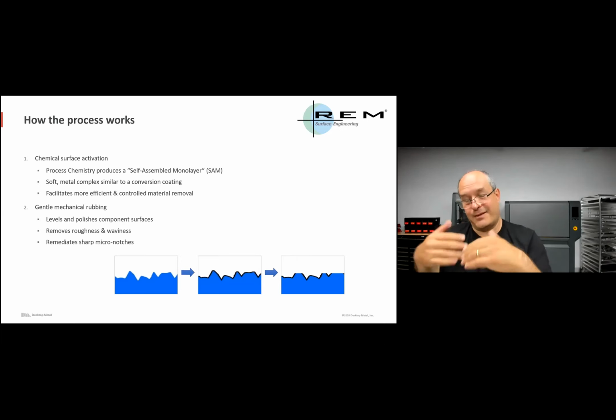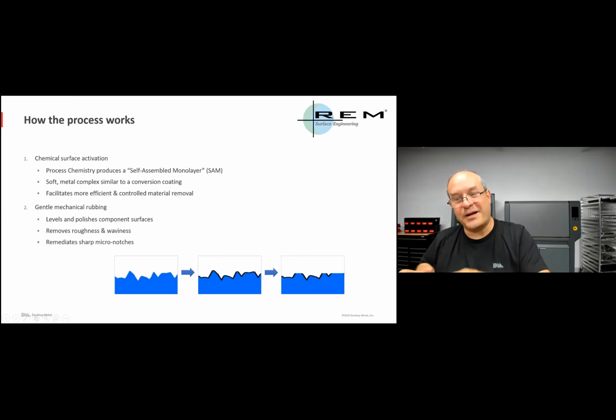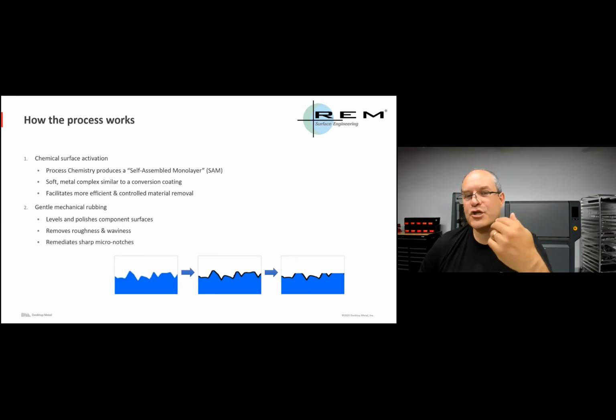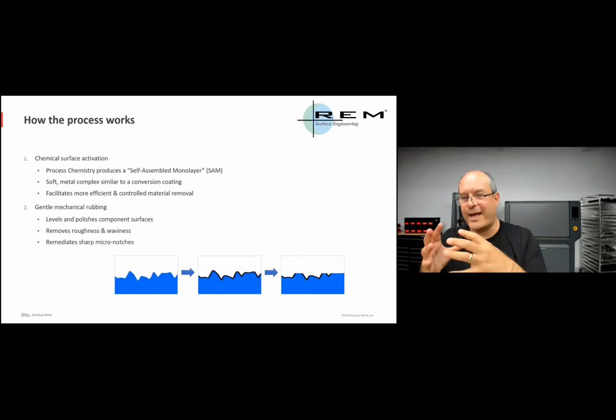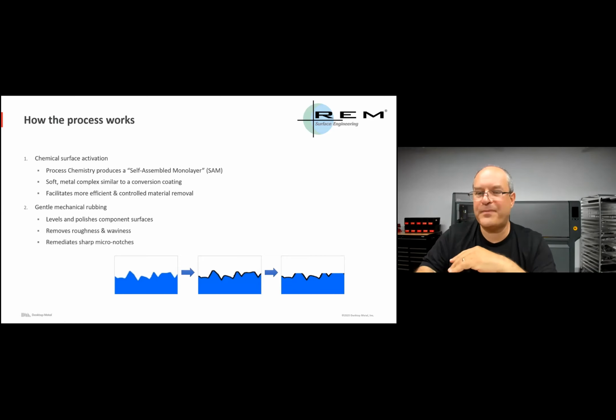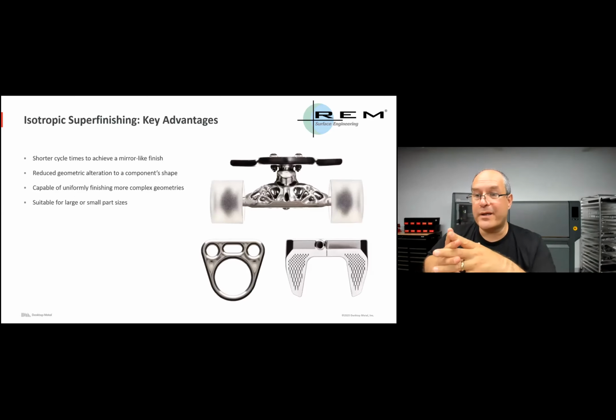But then remember, these peaks are still in that liquid, and so that surface activation reacts with those peaks and forms yet another coating, and the peaks are gradually worn away until you wind up with very smooth surfaces. The end result is parts that have that mirror-like, amazing finish with 100 nanometers or even better surface finish, but with a much faster time and reduced geometric alterations.